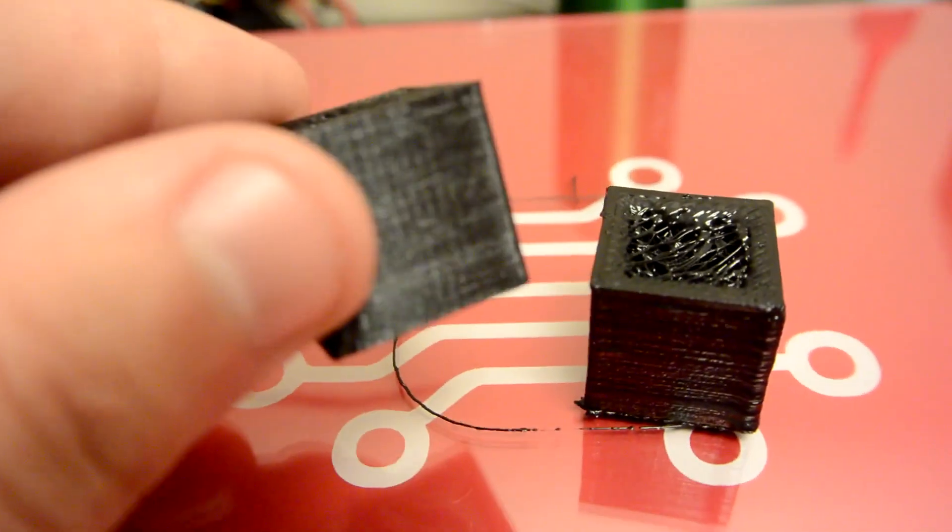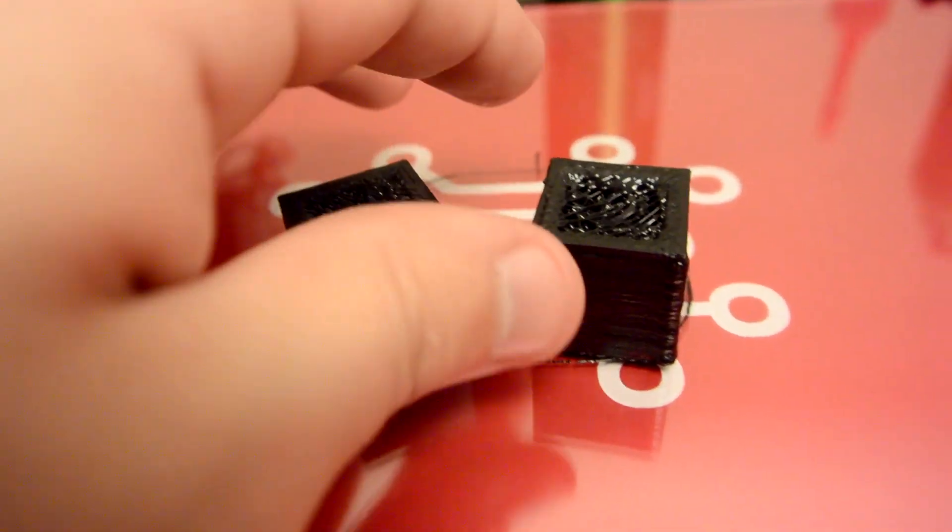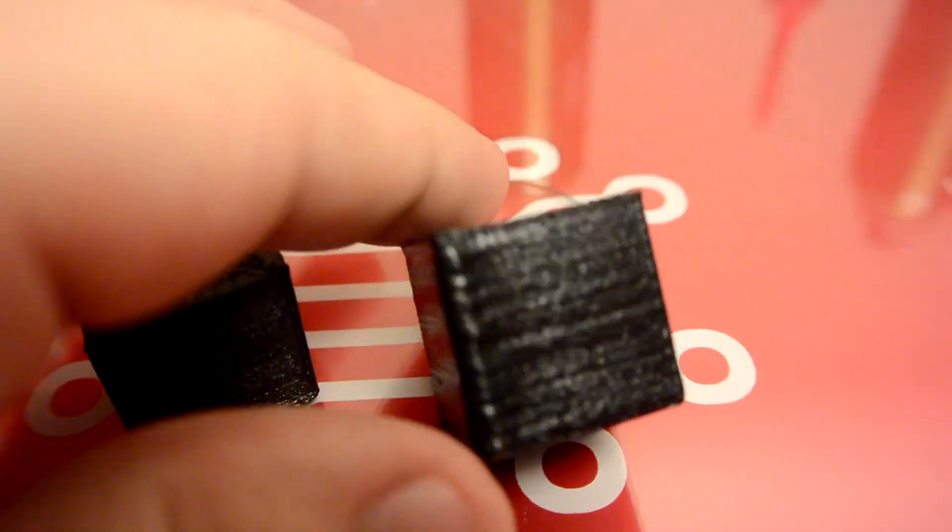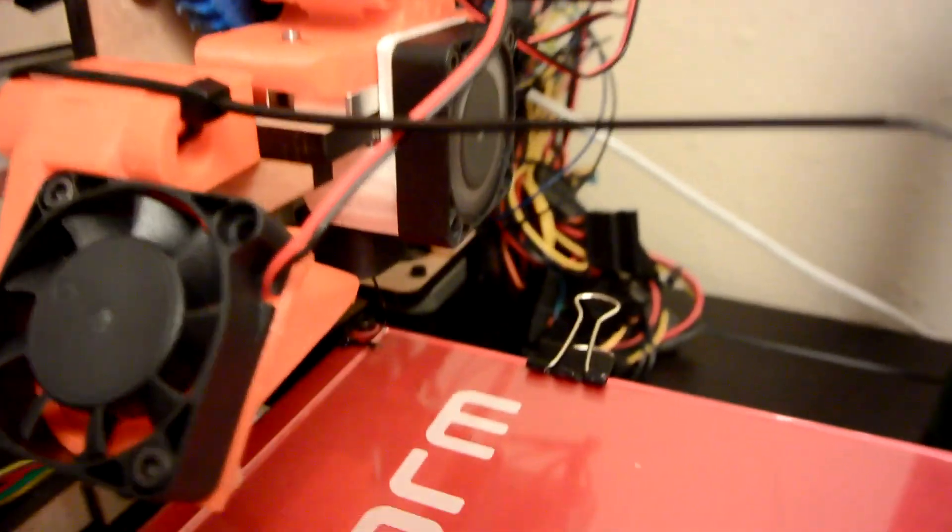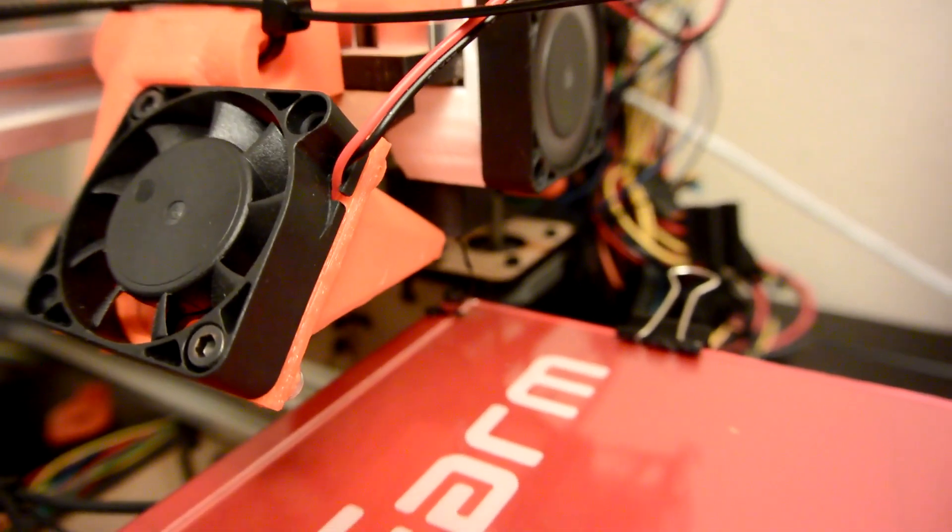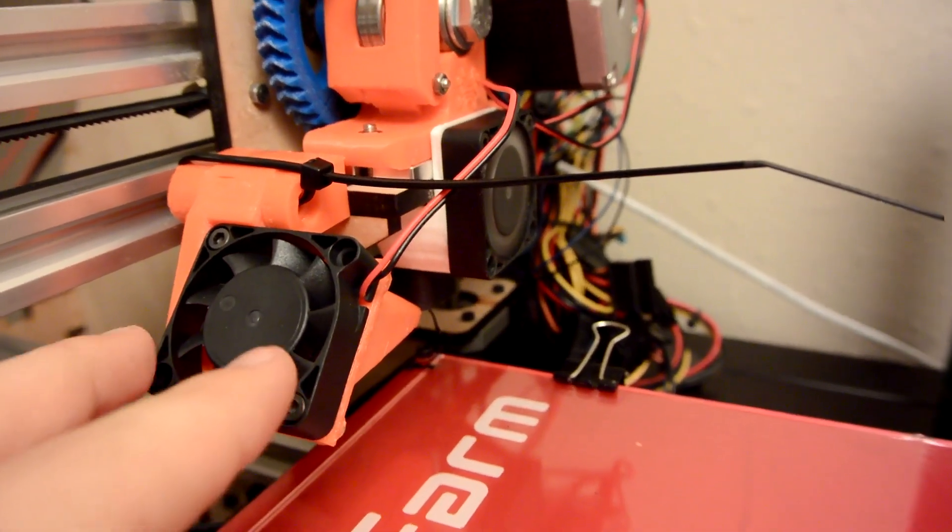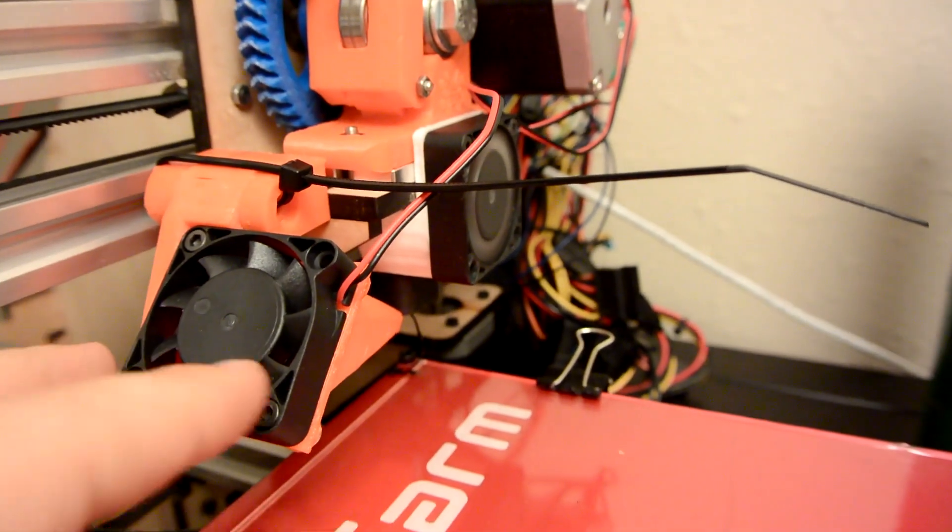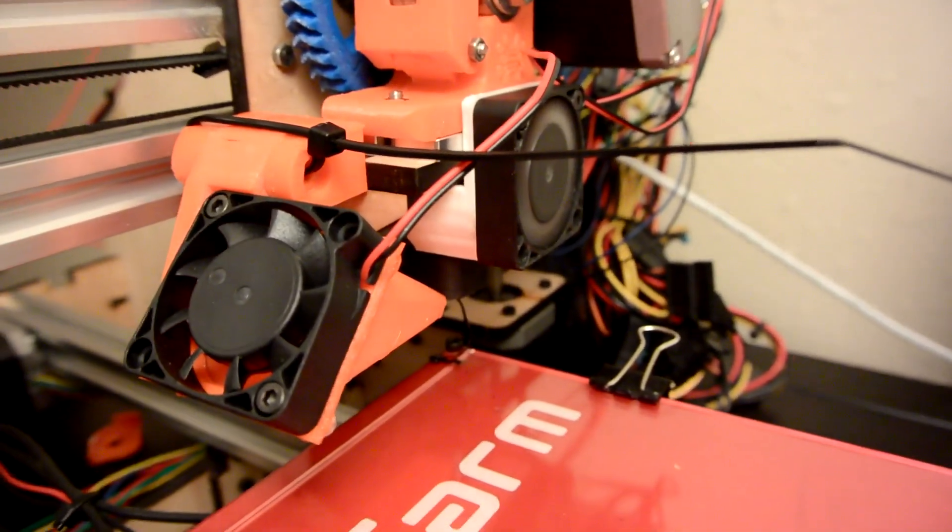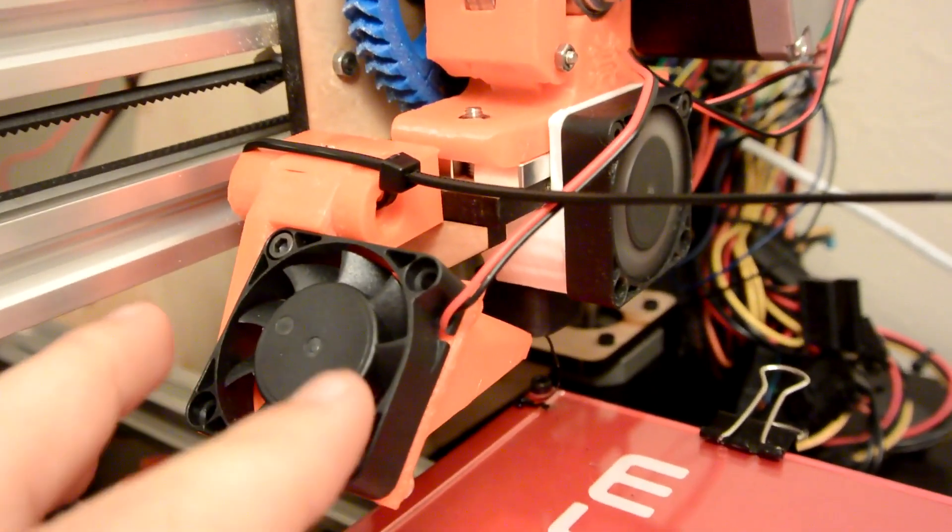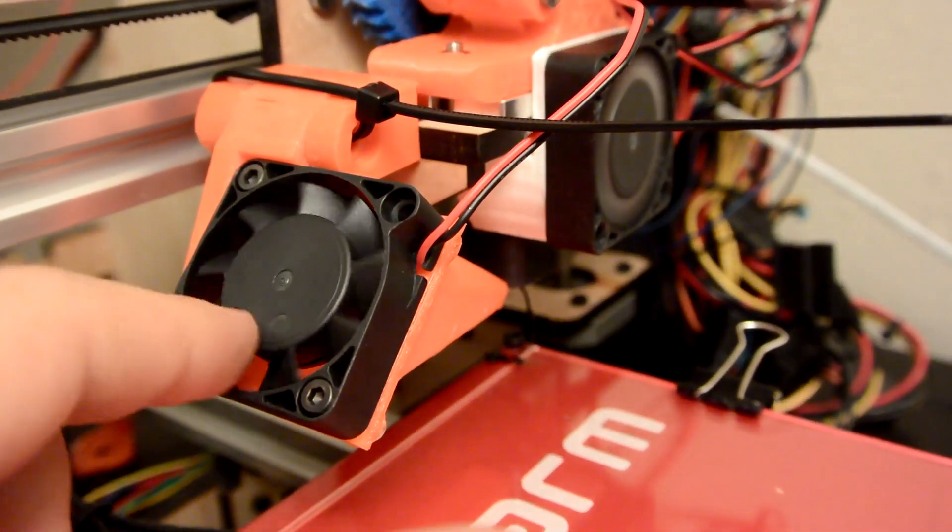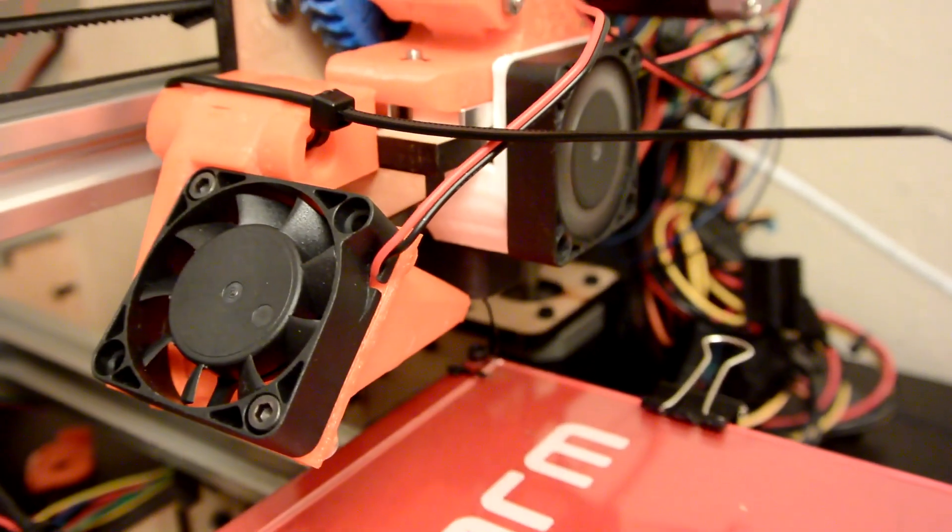And you can see even just on the side, the quality of the side there. It looks really good. There's not that much oozing. It's a much more consistent surface with the fan. So if you're printing something with flexible filaments or PLA, something that can withstand being cooled down, this fan is going to make a world of difference in print quality. I probably wouldn't recommend this and I probably won't use it myself for ABS because ABS tends to warp if it's not cooled consistently. But if you're using PLA or flexible filaments, play around with adding a fan to cool your prints. It might make the world of difference.